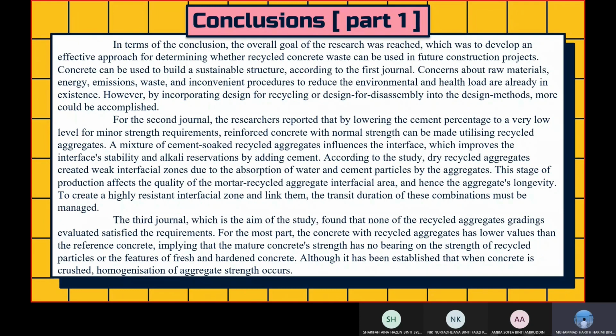For the second journal, the researchers reported that by lowering the cement percentage to a very low level for minor strength requirements, reinforced concrete with normal strength can be made utilizing recycled aggregate. A mixture of cement-soaked recycled aggregate influences the interface, which improves the interface stability and alkali reservation by adding cement. According to the study, dry recycled aggregate creates a weak interfacial zone due to the absorption of water and cement particles by the aggregate. This stage of production affects the quality of the mortar-recycled aggregate interfacial area, and hence the aggregate longevity, to create a highly resistant interfacial zone and link them. The transit duration of this combination must be managed.